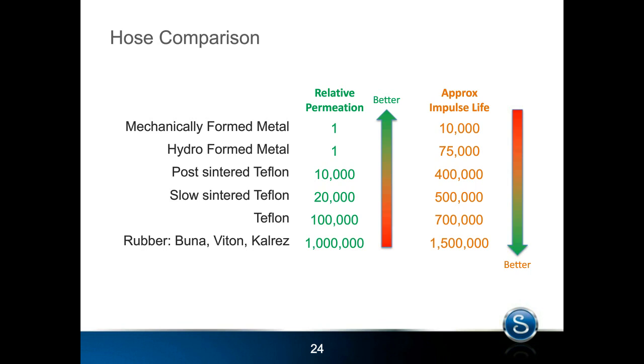So when we do that ball valve cycle test, we look and see how long the core tube will last. It's only 10,000 as compared to a rubber, which lasts well over 1 million. The hydroforming process spreads those stresses out, maintains the correct wall thickness in the core tube, and we get about 7 to 8 times the number of impulses out of a hydroformed core tube. So again, it's not quite to the level of Teflon still. Teflon, being a softer material, can absorb the pressure impulse much better, and we get hundreds of thousands based on the Teflon. But hydroforming metal does increase the impulse life a great deal.